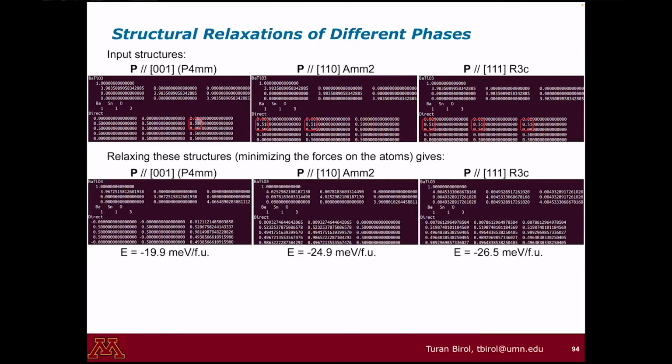And even though I start only with the titanium displacement, my Gamma 4 minus is also involved. I don't know if this is too small to read, but I think I can read it if I get a bit close to the screen and squint my eyes. It's not only the titanium that's displaced, but the barium is also displaced. And the 3 oxygens are also displaced, but notice that the last 2, for example, are displaced by equal amounts. So the resultant pattern preserves the symmetry, and hence it preserves some features of that original phonon mode that we found to be unstable, the Gamma 4 minus mode.